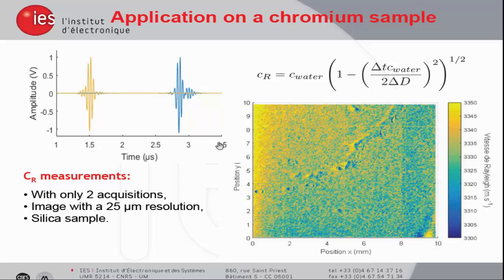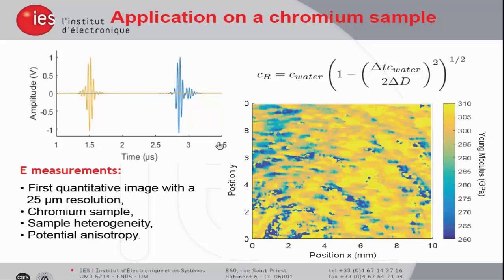The velocity range is between 3,300 and 3,350. So it's really highly homogeneous. And of course, it is in accordance with the value from the literature. So this was the validation of our protocol, and we applied it to a chromium sample.